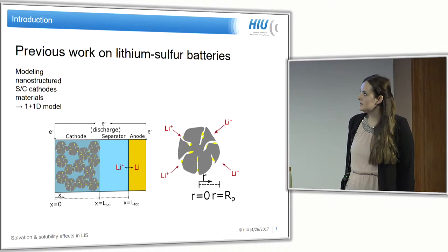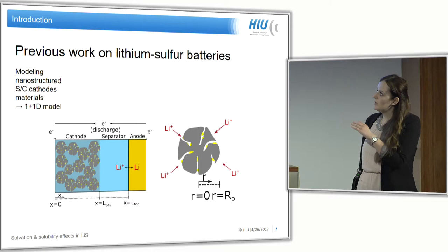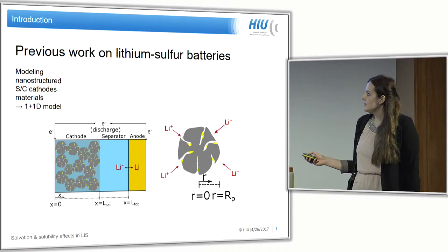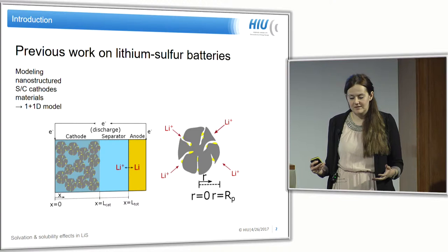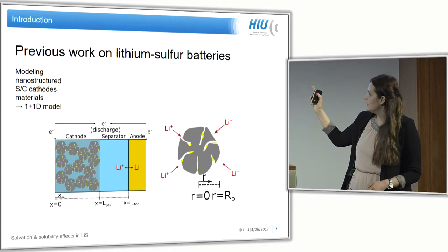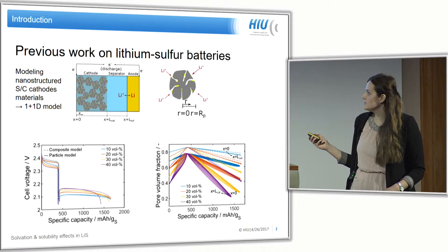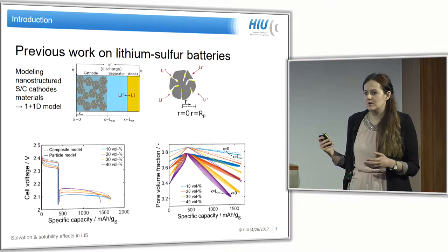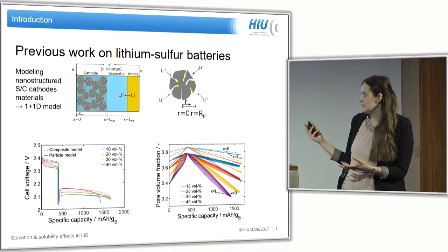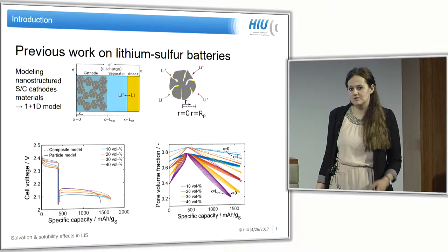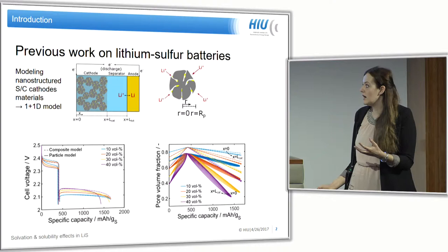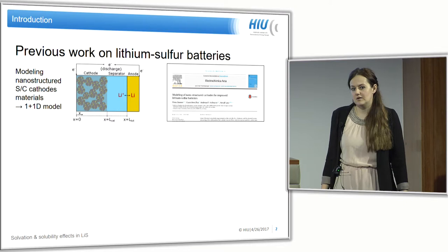Last year, we presented at this conference a 1+1D model for nanostructured carbon composite cathodes. We referred to the sulfur encapsulation in meso- and microporous particles and combined a microscopic cell model with a particle model for reaction and diffusion processes to combine cell performance with particle properties. This model allows us to investigate different sulfur loadings, identify limitations due to cycling stability, and additional transport limitations due to concentration inside the particle. This model is used as a base for further development.